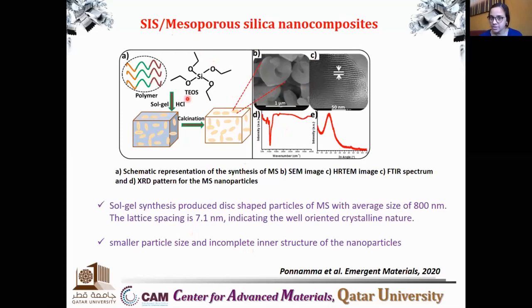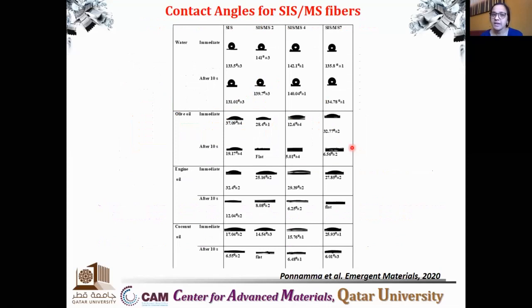And this shows the structure of mesoporous silica and how we are doing the sol-gel synthesis. And this is the disc shape. And these are the FTIR and XRD results confirming that we were able to synthesize the mesoporous silica. And these are the different contact angle values for the SIS and SIS mesoporous silica nanofibers. You can see that the contact angle value ranges from 133 to 142. So this shows that this is hydrophobic again. And with the oil, this is the olive oil, this is the engine oil, and this is the coconut oil.